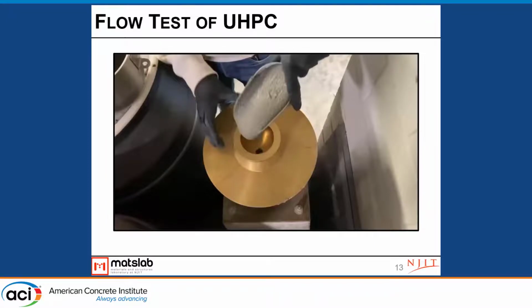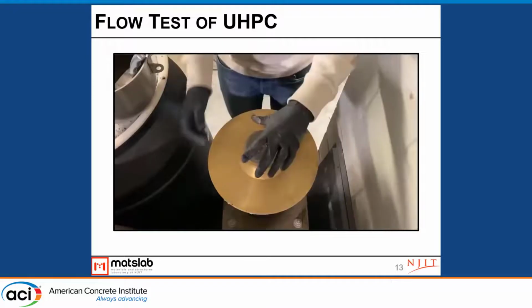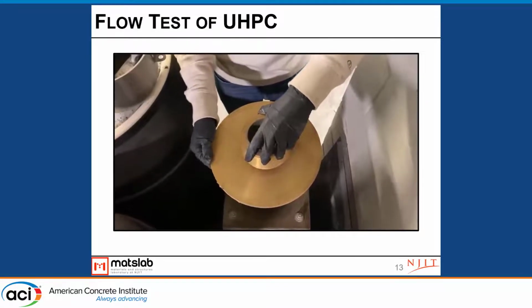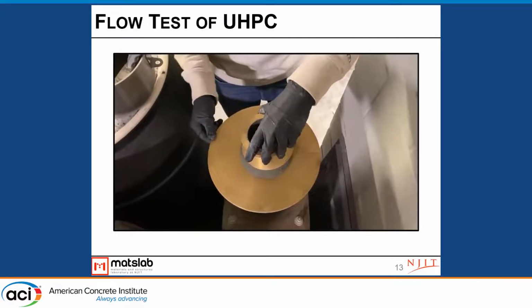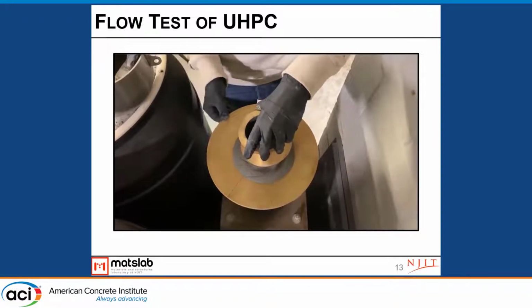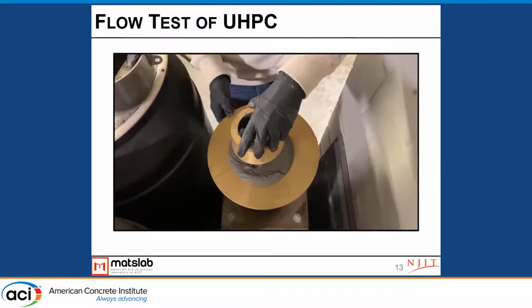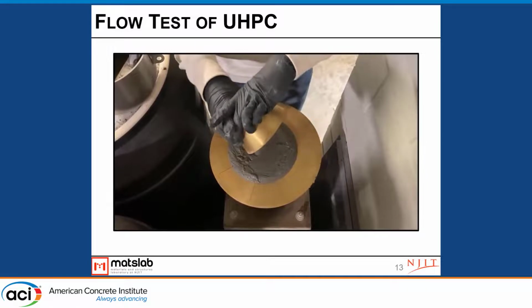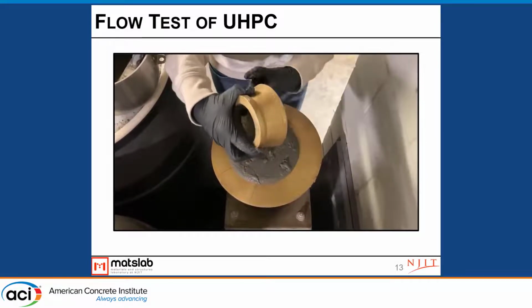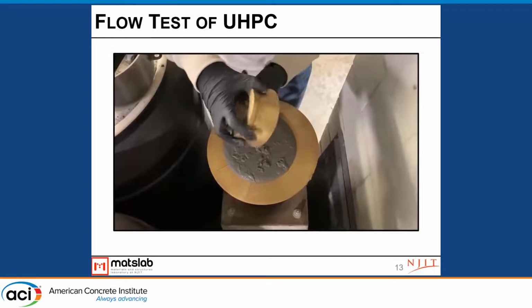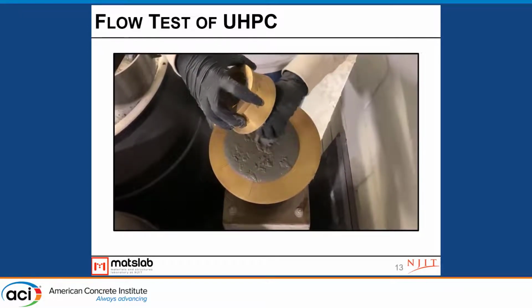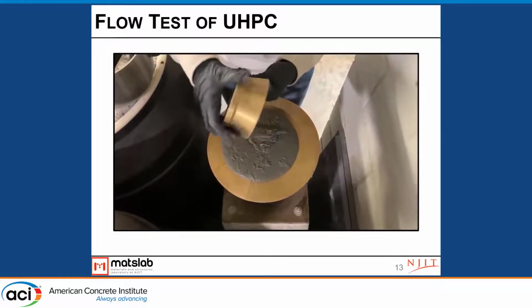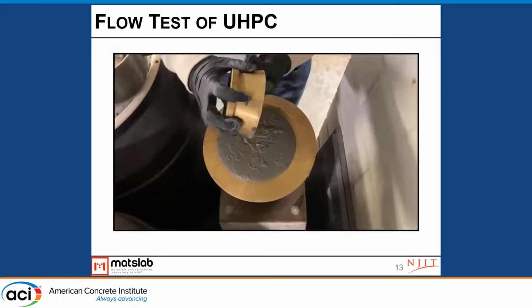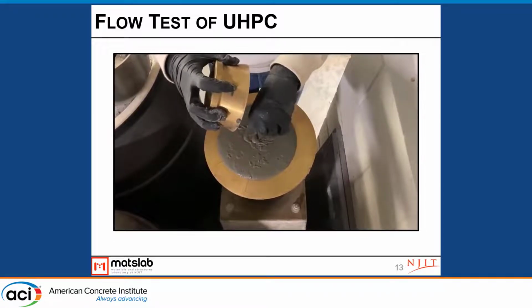At the end, you need to run a flow test to make sure the UHPC you have mixed is in the right condition. The flow test is pretty similar to the flow test we run for mortars. You need to fill up the rings with the materials, with some differences. For example, as you see here, you need to take off all the materials and add them onto the UHPC because these materials are sticky, specifically if you have a high volume of silica fume in your mix. You add the materials and let them rest for some time, like 1 or 2 minutes, and then measure the flow.